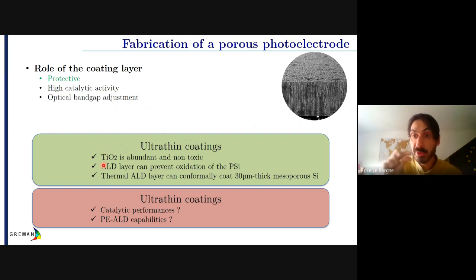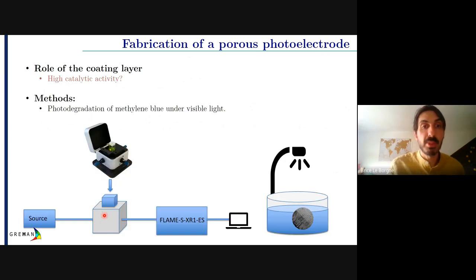So ALD layers, even the thinnest ones, can prevent oxidation. When you do only one cycle, the risk is to not have a homogeneous layer, or to leave holes in the layer. So we were using only 5 cycles. Maybe it's possible to go below, but it's not so easy. And thermal ALD, which is the normal one without plasma, can coat these pores, even in 30 micron thick layers. Probably it can coat thicker ones, but we didn't go further. What about the catalytic performances and the plasma capabilities? That's something we will discuss after.